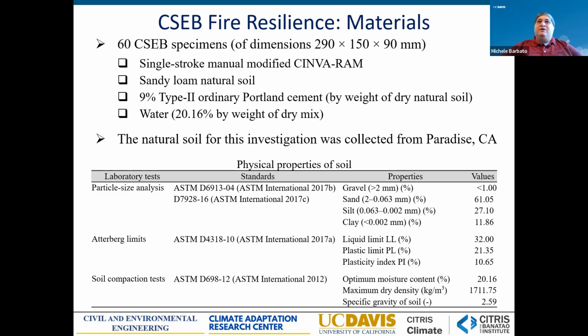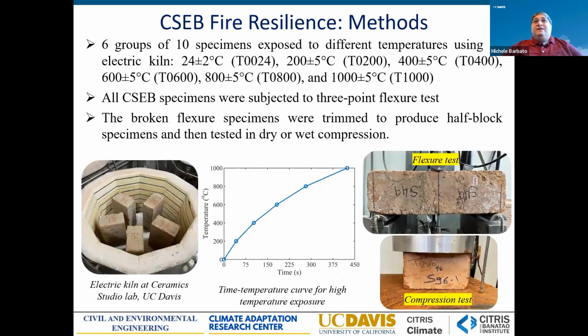We fabricated 60 blocks with the CINVA-RAM using a soil that was collected from the town of Paradise in California, the town that is unfortunately famous for being completely destroyed by the Camp Fire in 2018. And with that soil, a 9% Portland cement, we fabricated these blocks. Then we divided them into 6 different groups that were subjected to different temperature in a furnace. We left 10 blocks at room temperature, and then 10 were tested at 200 Celsius, 400 Celsius, 600 Celsius, 800 Celsius, up to 1000 Celsius for a prolonged period of time.